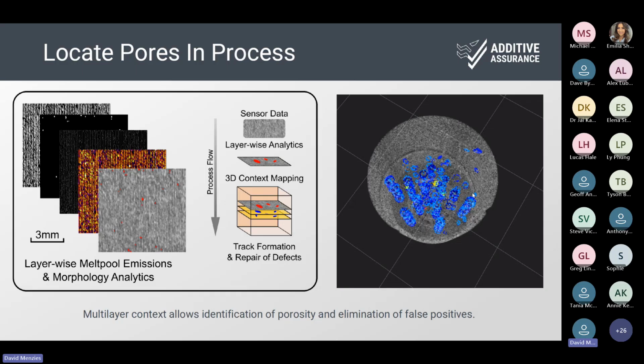And especially with lack of fusion, the defect size that becomes critical is a bit smaller than that resolution. So anywhere above 100 microns is where you want to be able to have a lot of confidence that you are seeing an issue.